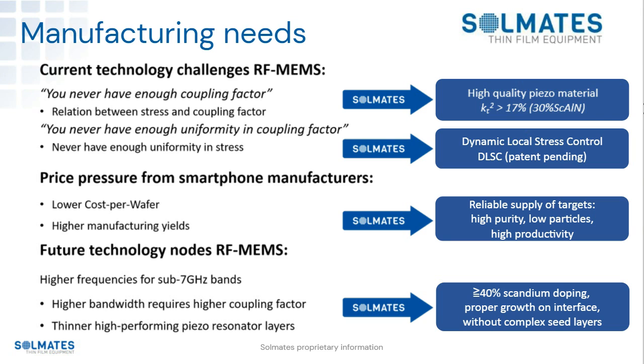So in the future technology, with the higher frequency bands in the sub-7 range, the resonance frequencies go up. So the layers become thinner. And as the layers become thinner, you need really good quality material, but you also, in terms of optimizing the coupling factor, you need even higher scandium doping. So we will show you one slide, the proof in the pudding. We did also some work on 40%. It works well, so hang in there.